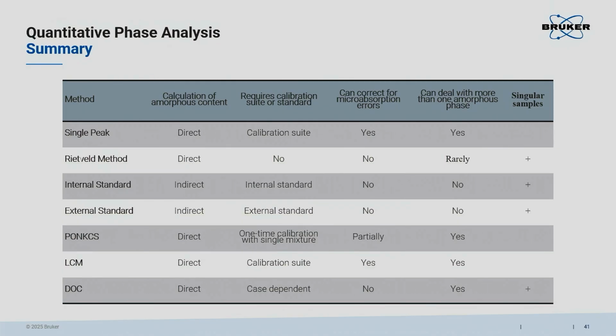What you do is simply determine a linear function. In case of doubt, you form a calibration curve. And later on, you simply, for example, correct your Rietveld refined results with a calibration function. And degree of crystallinity. We can see here which of the methods are suitable for direct or indirect quantification of amorphous content. The Rietveld method can do direct. The internal standard method can also do indirect.